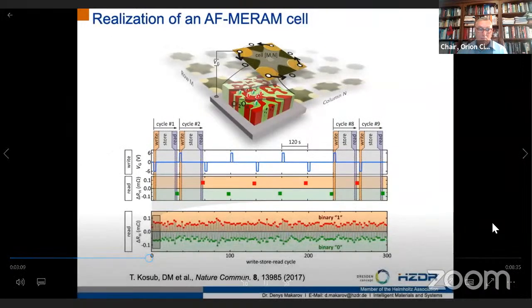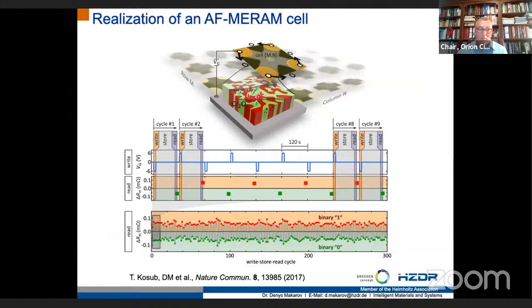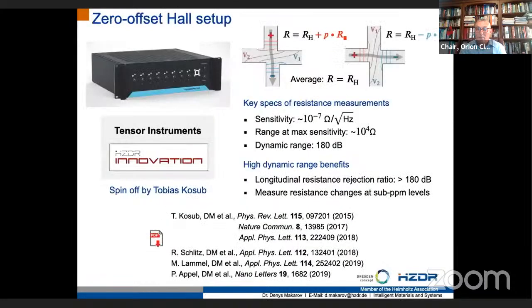The MRAM operation is demonstrated in this slide, where you can use electric field pulses to write information into the chromium oxide. You can store the information in the antiferromagnetic order parameter and read out information using the platinum electrode. And you can repeat this many times, mimicking the operation of conventional MRAM. To enable such kind of measurements, we rely on a zero offset Hall preset of the tensormeter device, which allows us to reject any parasitic leakage of longitudinal resistances in the transversal resistance channel, meaning that we will have the pure transversal resistance, which is the quantity related to the antiferromagnetic order parameter of chromium oxide thin film.